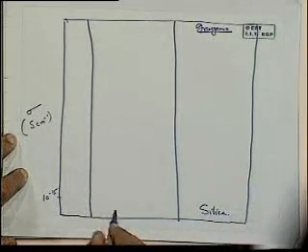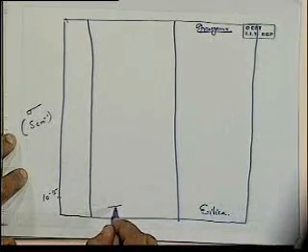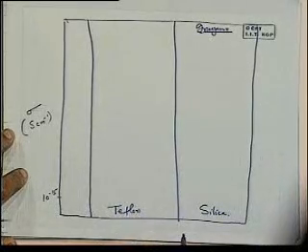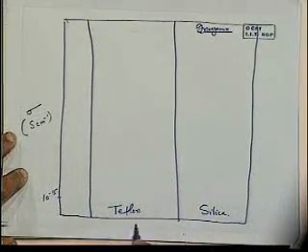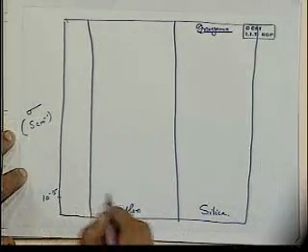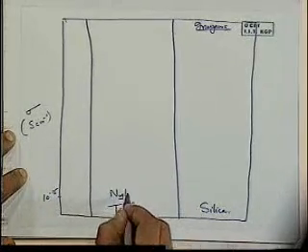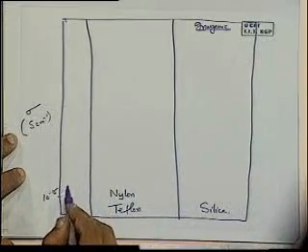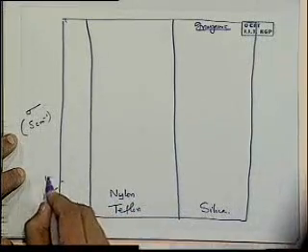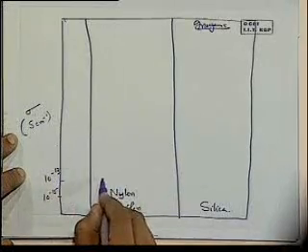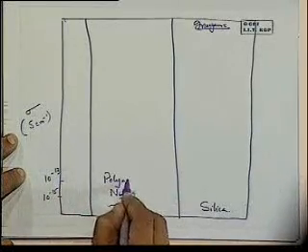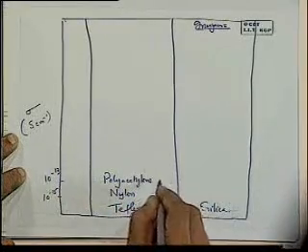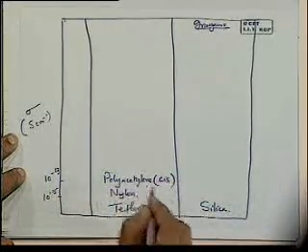In the organic world, it has a counterpart, Teflon. Very insulating. And then when you go a little higher, you've got nylon. And then about 10 to the power minus 13, we've got polyacetylene in a particular form known as the cis form. This is one of the isomers.